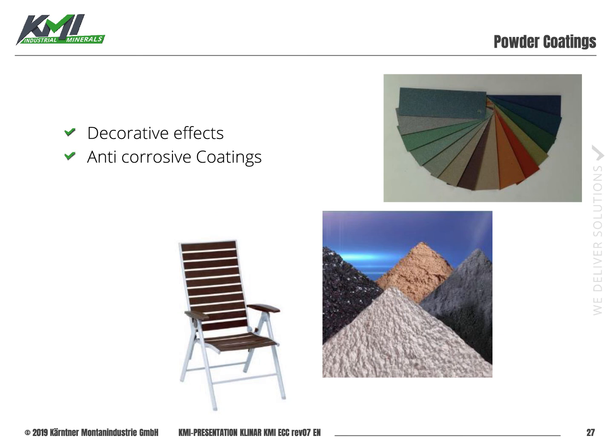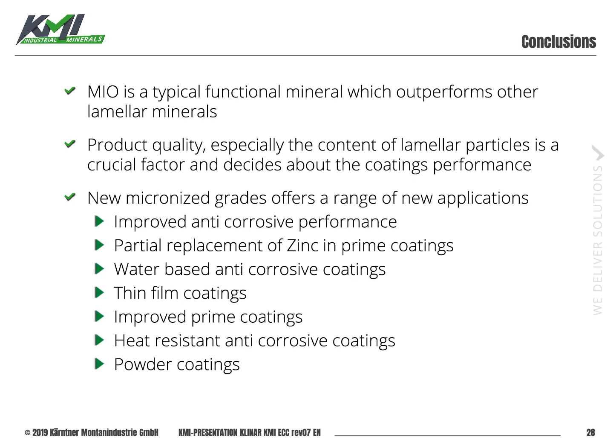But now, with the micronized grades, you have two things working in the right way for you. The first is they are much more efficient. That means the necessary loading level to get a good corrosion protection is much lower. And on the other hand, they are much finer, so you can apply much more in your powder. So with the micaceous iron oxide micronized grades, now you're also in a good position to create good performing anti-corrosive coatings on powder base. So at the end of the presentation, I will make the following conclusions.